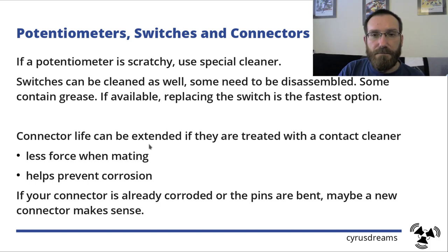That's a highly processed oil that you can spray on there. And what will happen with the connector is you have less force when mating the connector, and it helps a little bit to prevent corrosion. And even if you have less force when mating, you will not scrape off the plating of the connector so fast, and the connector will just multiply its lifetime if you do that.